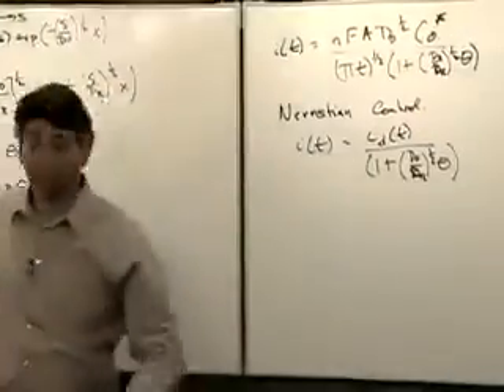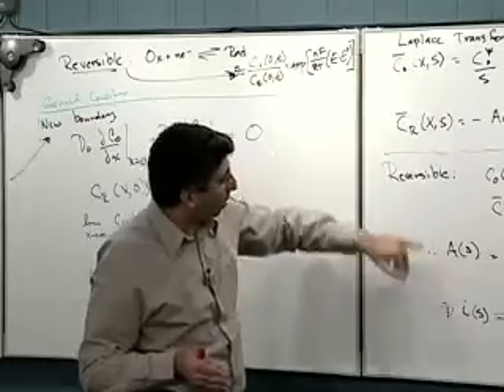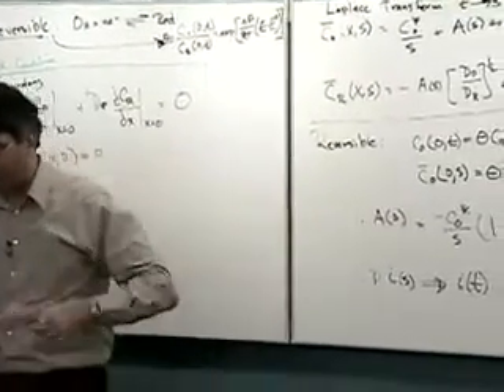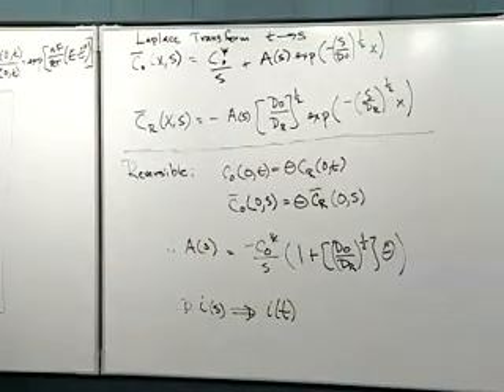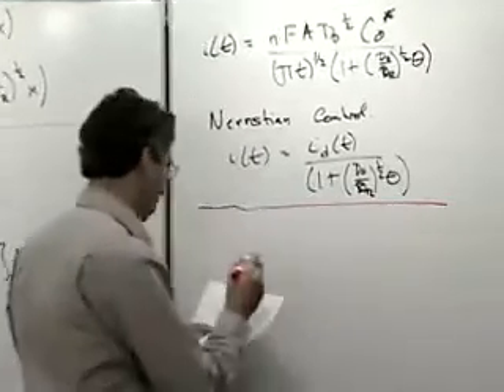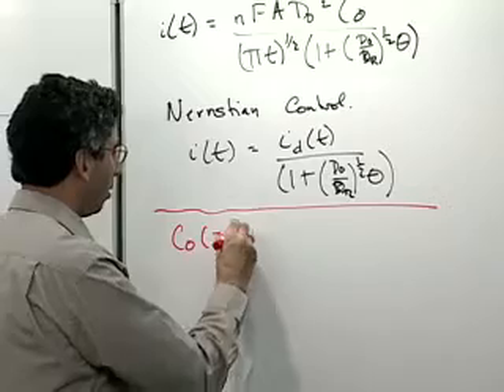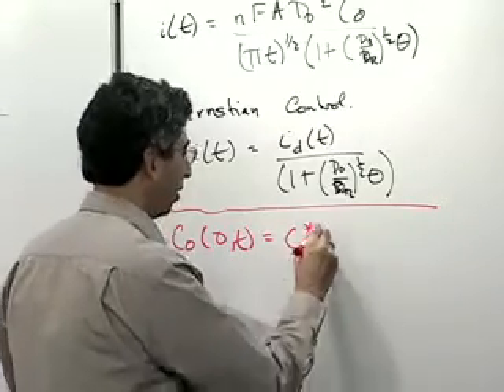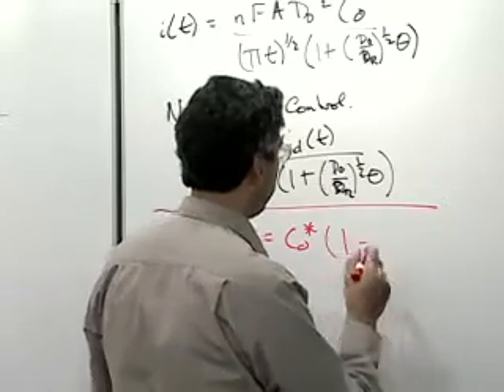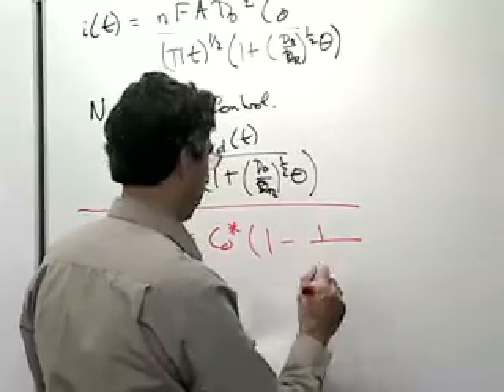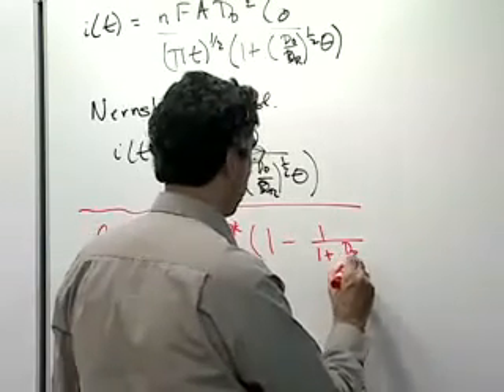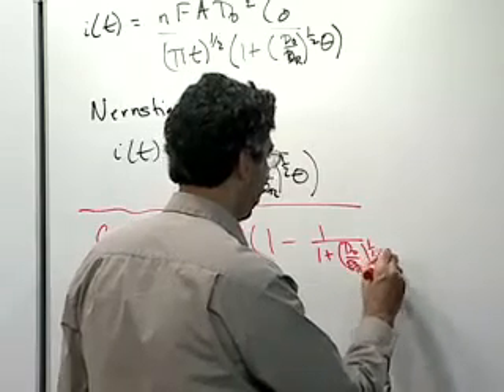Okay, well, before we leave this idea of the reversible Nernstian system, just one last comment to make, and that is quite obviously the current here is smaller than the current in the Cottrell case because the concentration gradient is smaller. And of course, I've worked out the concentrations here for you. You can plug back in, and then you'd have to reverse transform it. If you did that, hopefully it won't surprise you to discover that the concentration of the oxidized species at the electrode surface is equal to the bulk concentration times this term, essentially. In this case, it's a negative sign. 1 minus 1 over this 1 plus D_ox over D_red to the 1/2 theta.